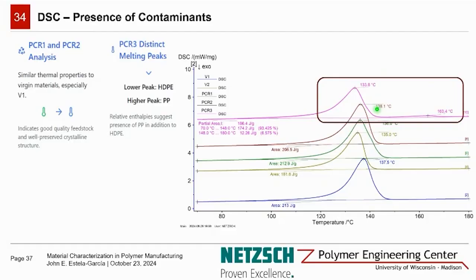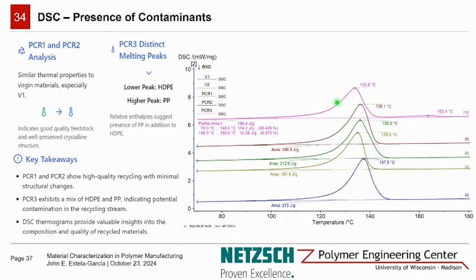It would require much more careful temperature control to ensure complete melting of both components without degrading the HDPE. We will also encounter inconsistent melt behavior, potentially leading to flow and distribution issues in the mold. Furthermore, the different crystallization rates of HDPE and polypropylene in PCR could result in uneven shrinkage, warpage in the final product, and this composition can also impact the mechanical properties that we have seen, potentially reducing strength and impact resistance.